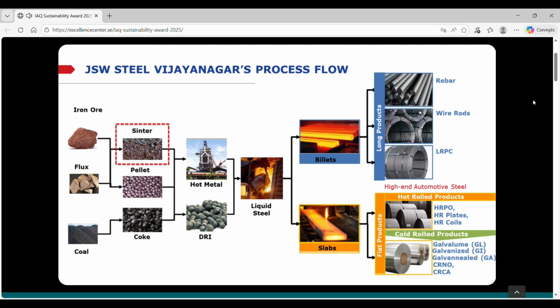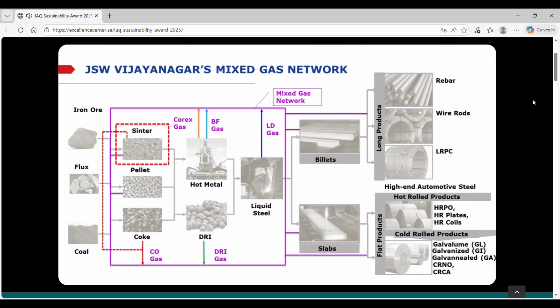The steel scrap and DRI are charged in electric arc furnace to produce liquid steel. The liquid steel is cast in continuous casting machines to produce slabs and billets. The slabs are rolled in hot strip mill and cold rolling mills to produce flat products. The billets are rolled in wire rod mill and bar rod mills to produce long products. The byproduct gas generated from coke oven, Corex, blast furnace, LD, and DRI are mixed and called mixed gas. The mixed gas is used for various heating applications in the entire integrated steel plant.